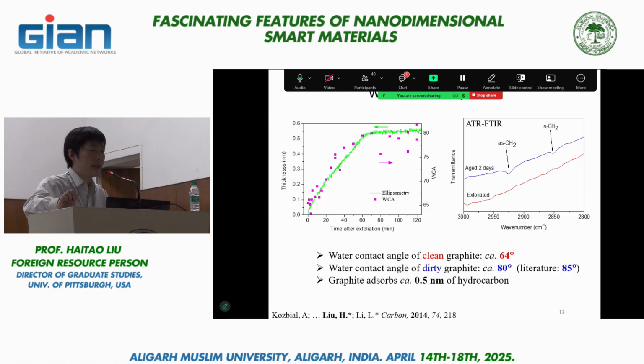As I mentioned before, contact angle, wettability, is directly linked to the surface energy: liquid-vapor, solid-vapor, and solid-liquid. So we'll be using water as a testing liquid, but you can do the same kind of measurement using organic or other inorganic testing liquids. By varying the testing liquid, you can change the liquid surface tension, and by doing that, you can extract the solid surface tension by using a certain mathematical model.